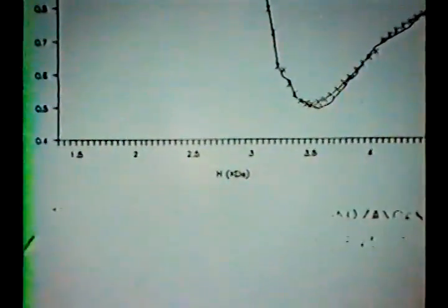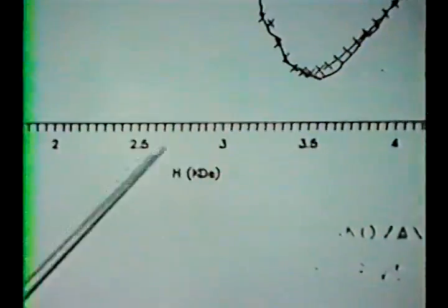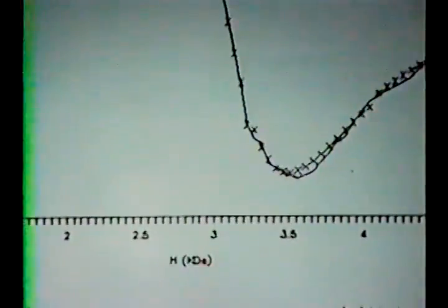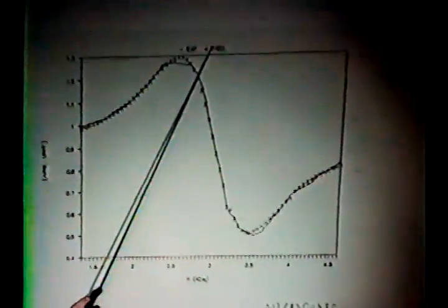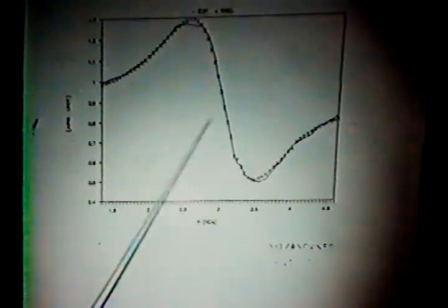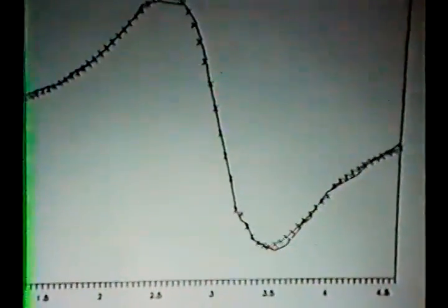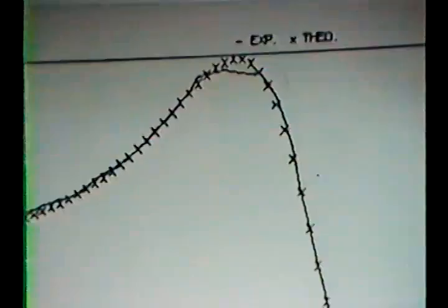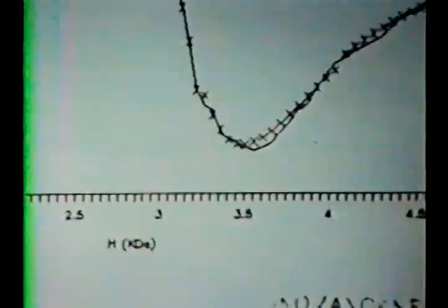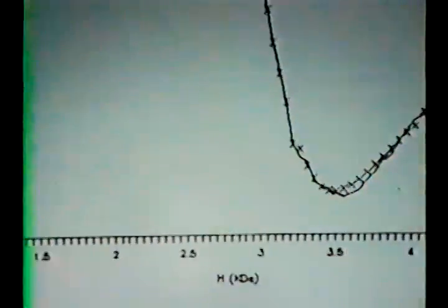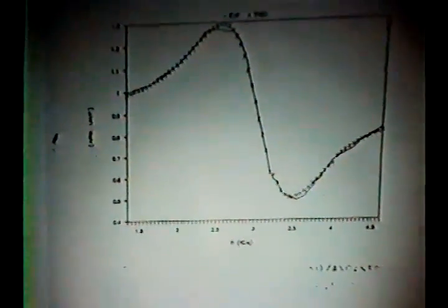This is an EPR spectrum on a ferromagnetic material, ferromagnetic resonance, FMR it's called. And this is just the intensity as a function of the value of the magnetic field in kilo-oersted. The solid line is experimental, and the x's are theoretical fit to the data. And for a super paramagnetic system, that means an extremely small particle that's single domain. All we mean by that is the magnetic moments in this material are all traveling together during this experiment, and they're all the same. There's one domain. All the magnetic moments are aligned.